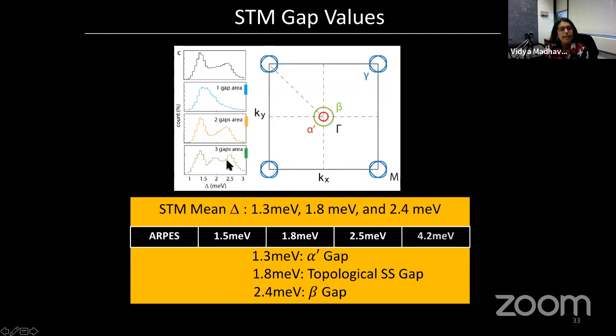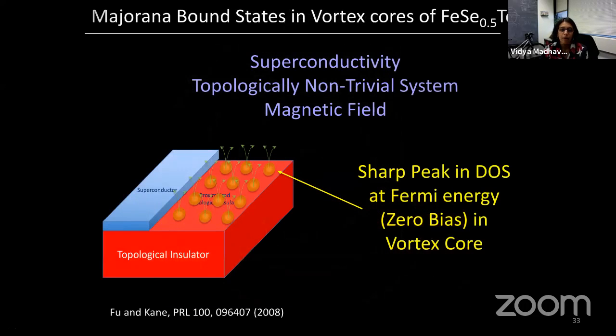Let's look at this last histogram here. You see 3 distinct gaps with the STM. The mean gap values we get are 1.3, 1.8, and 2.4 meV. If you compare that with ARPES, we can identify the 1.3 millivolt gap with the alpha pocket, the 1.8 millivolt gap with the topological surface state that I was telling you about earlier, and the 2.4 millivolt gap with the beta pocket. So we can see all of these different gaps from the different pockets.